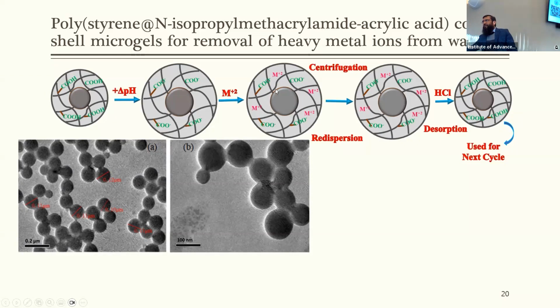And the core shell microgel particles containing the metal ions can be removed from the water by a simple centrifugation method, and then these microgel particles containing the heavy metal ions were treated with HCl to displace the metal ions by hydrogen ions, and the system is converted from negatively charged core shell microgel to uncharged microgel particles, and this system can be reused as an adsorbent for removal of toxic chemicals from aqueous medium.